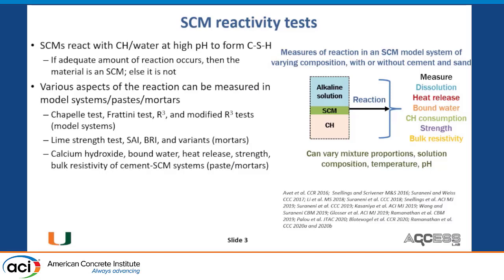You can measure all of these different aspects in model systems, in paste, in mortars. A lot of different tests exist to do this — Chapelle, Frattini, R3, modified R3, et cetera. Now, some of these tests are a lot more difficult to interpret than others. For example, if you run in cement paste and mortars, the issue is simply that OPC is an order of magnitude more reactive than SCMs. So if you measure a heat of hydration test of OPC with 20% SCM at seven days, you measure for the most part the response of the OPC — your SCMs are simply not reacting enough.